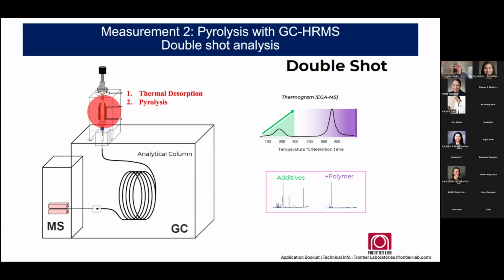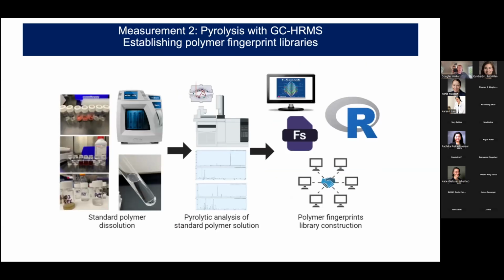However, it's not hot enough to combust the particles themselves. So after this thermal desorption step, we then pyrolyze the samples, which is when we heat them to 650 degrees, and that causes the breakdown of the polymers to the individual products.